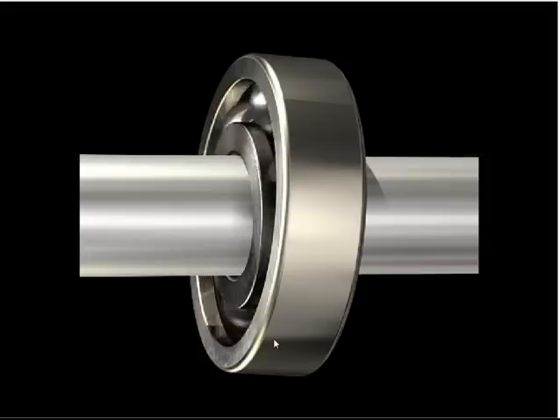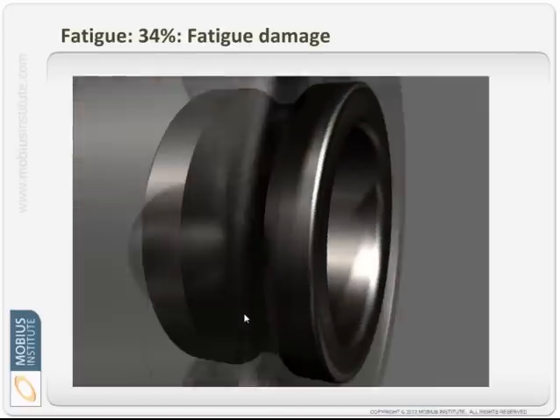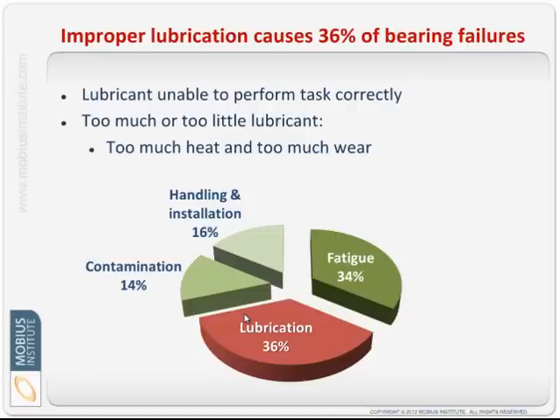If the bearing was not installed properly and the outer race was cocked slightly, you can imagine the additional load these rolling elements and therefore the raceways are under. It's worth pointing out, we'll dwell on this a little more later in the presentation, but when we open a bearing, when we decide to replace the bearing, we take it out and look at the raceway, you can see patterns on the raceway which tell you why the bearing failed. And if we saw a pattern like this, we can tell it's because of excessive load.